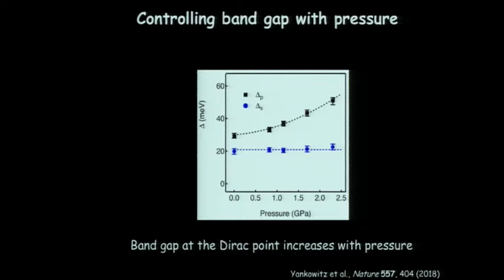So there is an out-of-plane signal, right? There's a delta Z signal that we see, but we can't be certain that it's a pure topographic signal and it isn't also a density of states effect which is causing the tip to also modulate. So the calculations say that there should be a small out-of-plane modulation, and we see an out-of-plane modulation, but I can't guarantee that it's not an electronic effect on top of a topographic effect. Did you do this in your AFM?